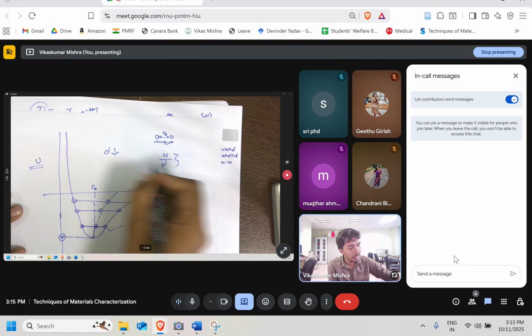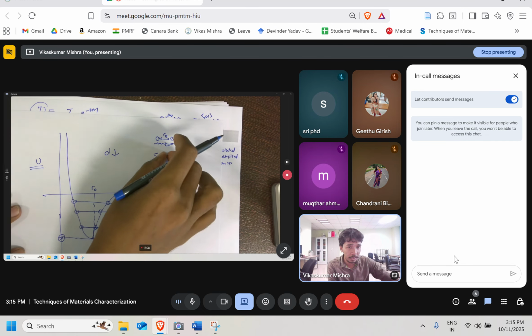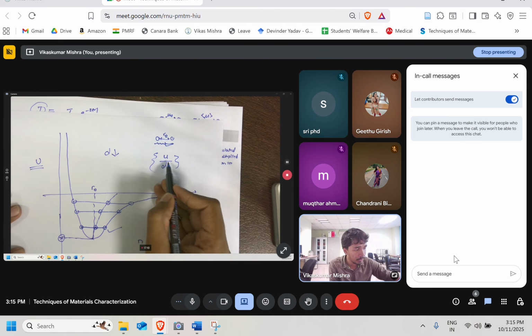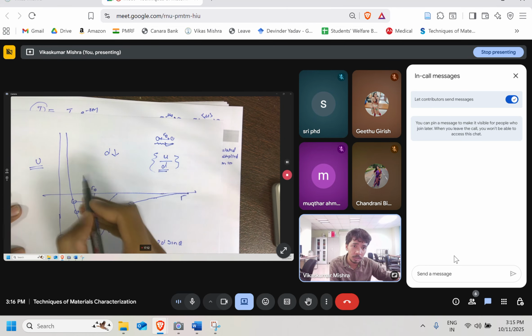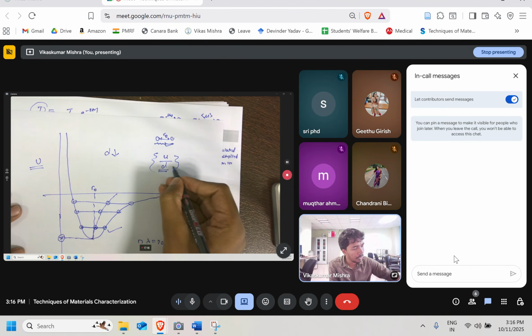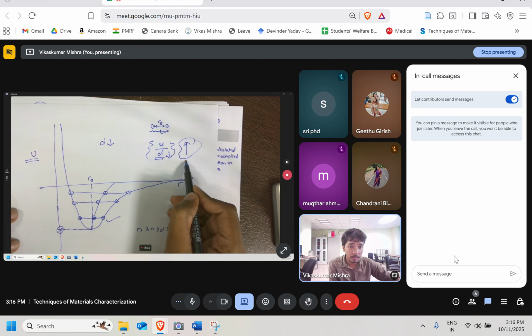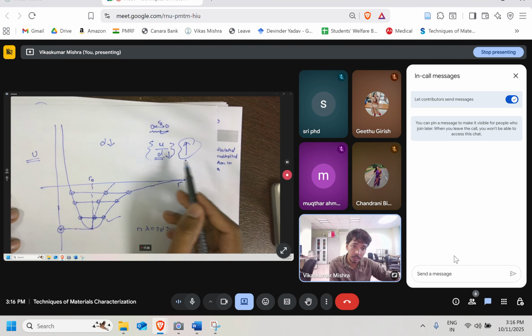This can significantly affect this entire term. A small vibration can affect the smaller d value more effectively compared to the larger d value. This is why, if I keep on decreasing d, the entire term overall is going to increase, and so it can lead to destructive interference.